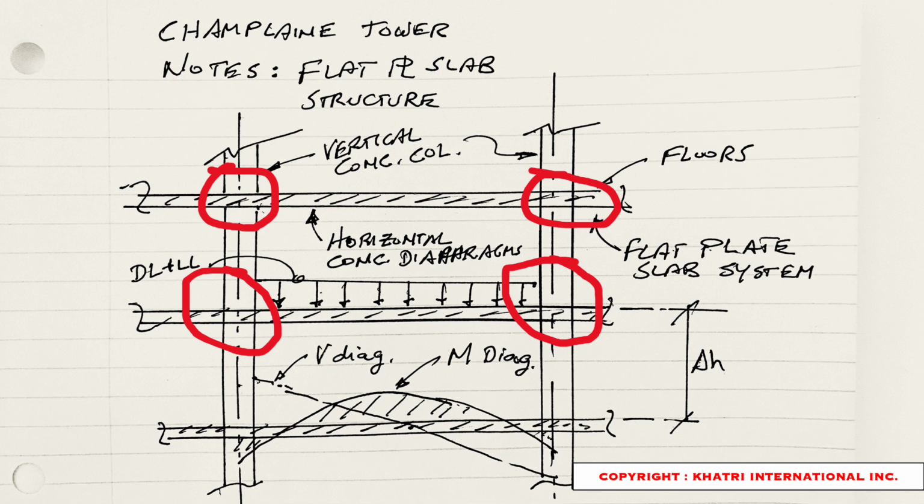And if the rebar is truly corroded, then if you don't have enough embedment length, which is the length of steel required for it to tie itself to the vertical columns, then that would pull out and it would cause a total collapse of the floor system.